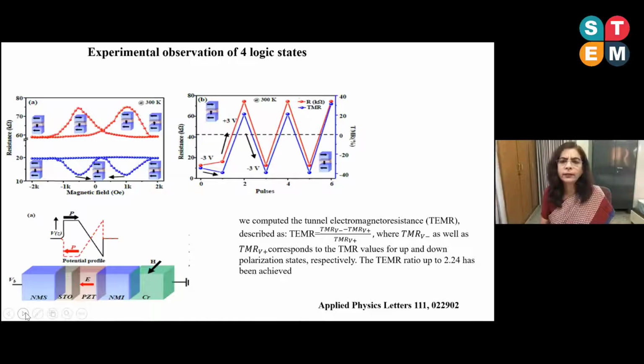Then we measured the experimental observation of the four logic states, in which the magnetoresistance was measured in the magnetic field, varied from 0 to 2K. We saw one state for the upward polarization, and another for the downward polarization. So states 1, 2, 3, and 4 were observed experimentally.